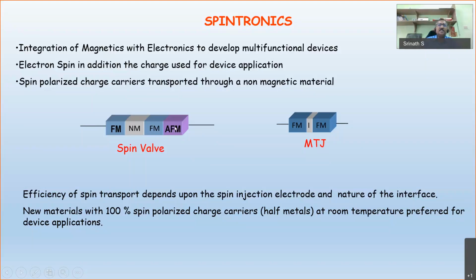So what my interest is, let us say this ferromagnetic layer, the magnetization is pointing up. And this is pinned with this antiferromagnetic layer so that this fellow is pointing up. How I do it is left to me, but I am saying there is an antiferromagnet which holds this fellow so that it doesn't flip. It is parallel, let's say plus Z direction. Whereas the magnetization in this ferromagnetic layer, by applying a magnetic field or electric field, I can flip either up or down, without affecting this fellow, because there is a spacer layer separating these two fellows. That is my geometry, that is my construction.